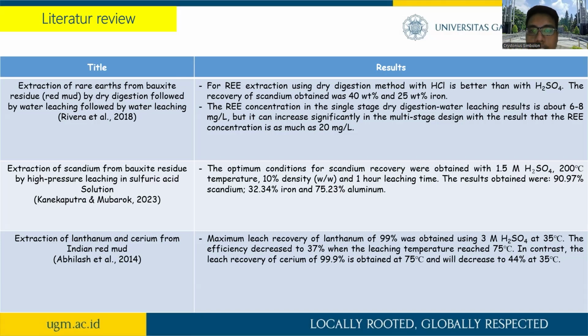The REE concentration in the single-stage dry digestion water leaching result is about 6 until 8 mg per liter, but it can increase significantly in the multi-stage design, with the result that REE concentration is as much as 20 mg per liter. The second is extraction of scandium from bauxite residue by high pressure leaching in sulfuric acid solution by Kanekaputra and Mubarok, 2023.